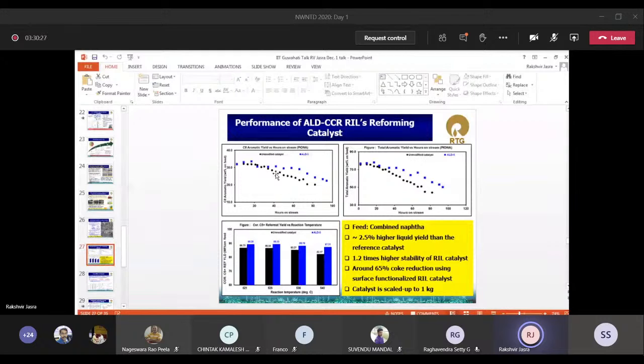And here, a few percent, 2.5% higher liquid yield, means millions of rupees to us because our plant is very big. So we got 2.5% higher liquid yield and stability was 1.2 times higher, with 65% less coke. It means sintering is not happening and also coke is not forming and we are getting better yields. It means a lot. So this is what we could do.